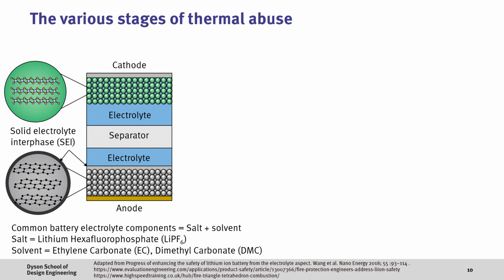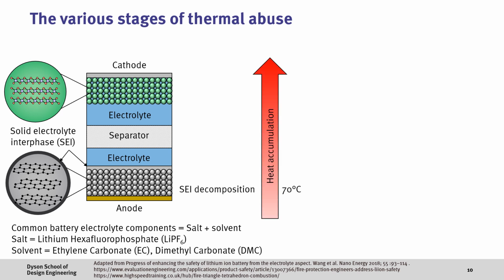In most battery systems, the liquid electrolyte is thermodynamically unstable with lithiated graphite. This basically means that this system shouldn't have good lifetime. However, the protective SEI layer stabilizes the graphite, allowing the battery to work. As the battery is heated to about 70 degrees, this SEI layer can decompose, revealing fresh graphite surfaces to the reactive electrolyte. As heating continues, the electrolyte and anode react with each other in an exothermic process which generates further heat.